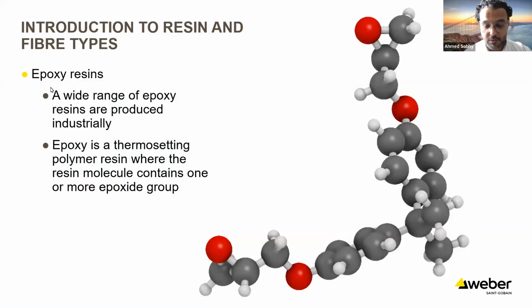We're quite aware that epoxy resins, or epoxy in general, is a petroleum derivative, and as a company and as an industry, we should be very much aware of the carbon emissions and the downfalls of using petroleum derivatives in fiber reinforced polymers or construction in general. We're very much aware of this. So when we're talking about a laminate or a finished product of fiber reinforced polymer, we're talking about a fiber to resin ratio of about 60-70% to 30%, fiber being the 60 to 70%. And with that low proportion of resin within the finished laminate, it has the highest contribution of carbon emissions in life cycle analysis. This 30% of resin contributes about 80% of the carbon emission of that product over its life. So it's a huge contribution.